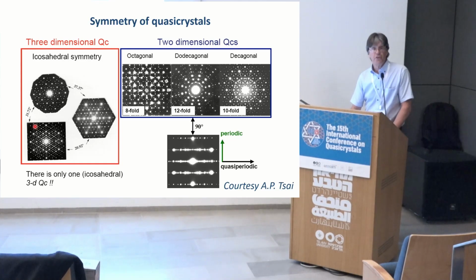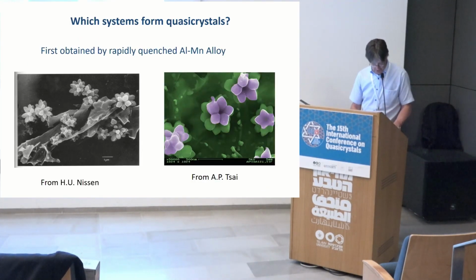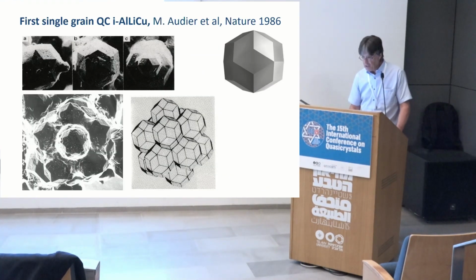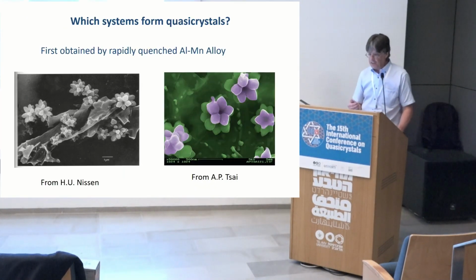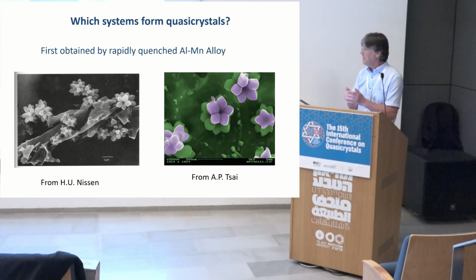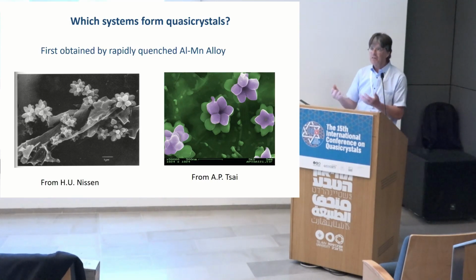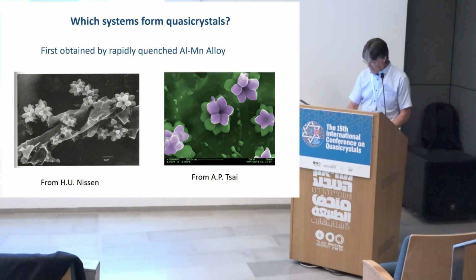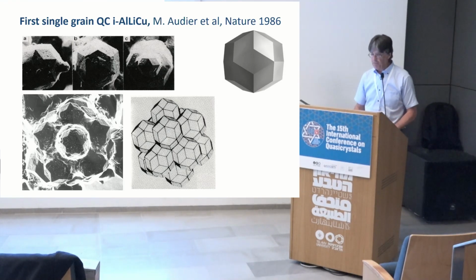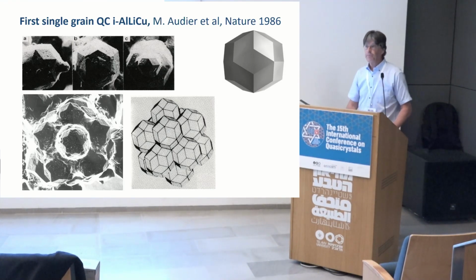But before going to the study of the structure, let's start with a little bit of history. So which systems formed quasicrystals? And that was a lot of debate at the beginning, because the first ones were only obtained by rapid quenching. So is it really long-range order? The first breakthrough came from Marc Audier. At that time, he was working at Pechiney on aluminum alloys. And during the study, they found this very nice quasicrystal single grain.